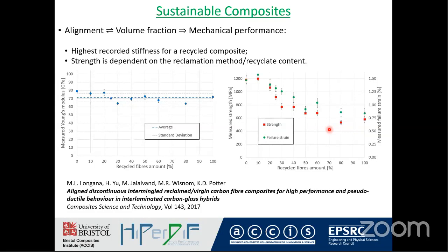So this is about sustainability, and as was very clearly made evident yesterday in Soraya's talk, was the need to combine alignment and high volume fraction of reinforcement to achieve good performance. Now, these data show for a carbon glass hybrid the highest recorded stiffness for a recycled composite. You can see the sort of values we're looking at for recyclate here, about 70 gigapascals. And importantly, as the amount of recycled fibers is increased in the blend, there's no discernible change in the properties.